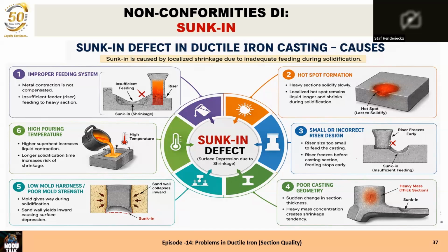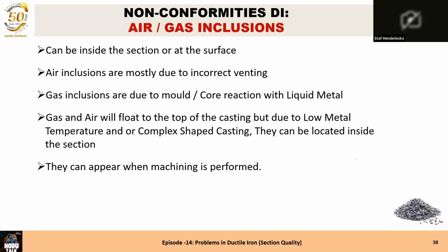A hotspot is a very dangerous area for any type of porosity. An incorrect riser design, of course, when the riser neck is solidifying very quickly, then the risk is very, very high that you get that sink-in. And the casting geometry is also important, because if the feeding length of the riser is not sufficient, you can get a sink-in over there. That was about porosity.